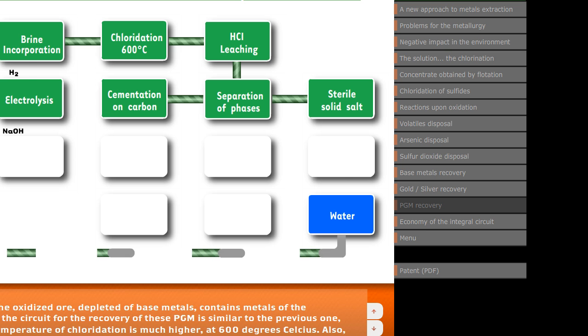In cases where the oxidized ore, depleted of base metals, contains metals of the platinum group, the circuit for the recovery of these PGM is similar to the previous one, except that the temperature of chloridation is much higher, at 600 degrees Celsius. Also, the leaching after chloridation is done with hydrochloric acid. The efficiency of this system is absolutely remarkable, a recuperation at the level of 98% of platinum being achieved with an ore at 1 ppm of this metal. The disposal of brines and the recycling of water, along with the use of activated carbon as metal accumulator, is identical to the gold collection circuit, and leaves a solid without capability of leachate generation.